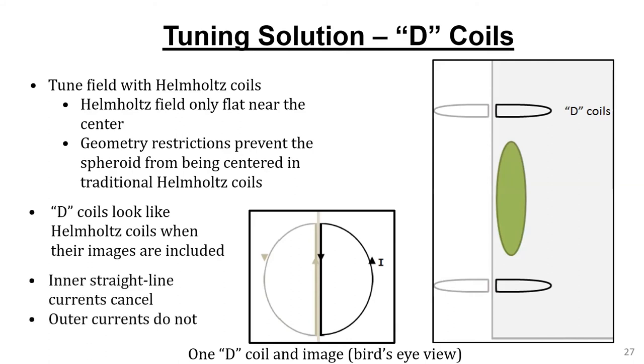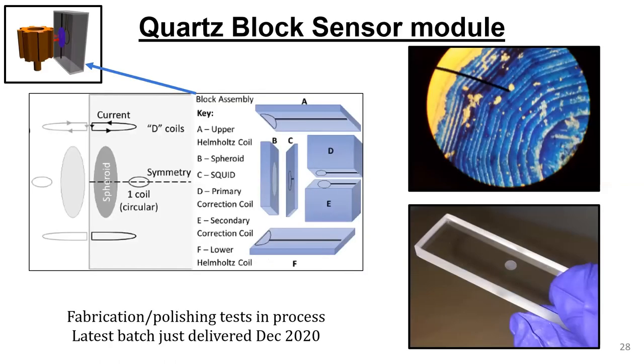And so in order to implement this in the experiment, our quartz block, which contains our helium-3 sample, needs to have these current carrying coils patterned into it. We have the quartz block assembled in sections here, where we have the spheroid, the sensing helium-3 chamber here. We have our compensation coil for the gradient cancellation, as well as the current coils for setting the bias field for the Larmor precession frequency, all patterned into the same block. We've done some fabrication and polishing tests for fabricating these spherical cavities. We're trying to refine that. We just got our latest batch delivered a couple days ago, so we're excited to attempt constructing this quartz block sometime soon and checking the performance.